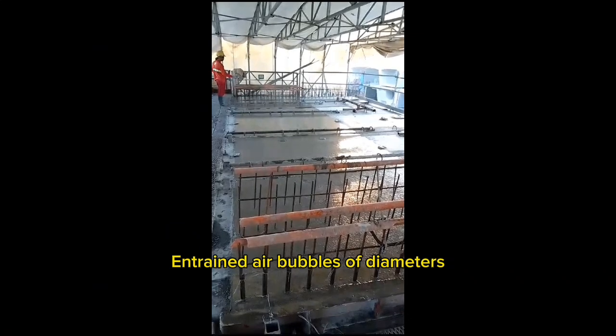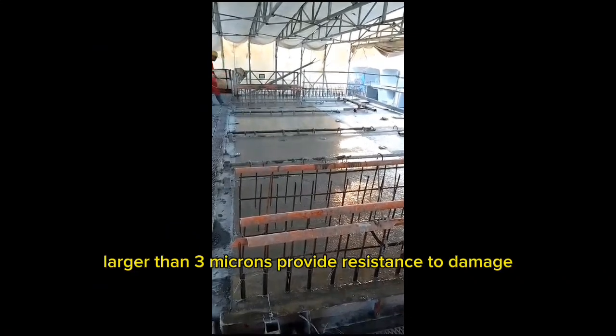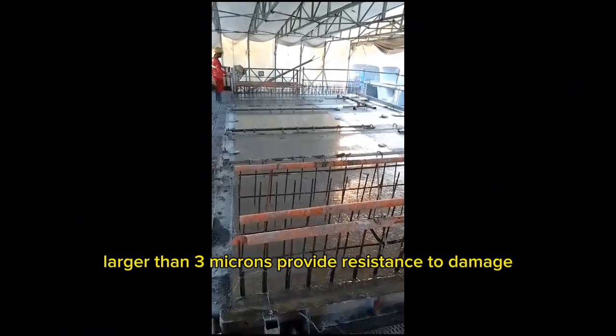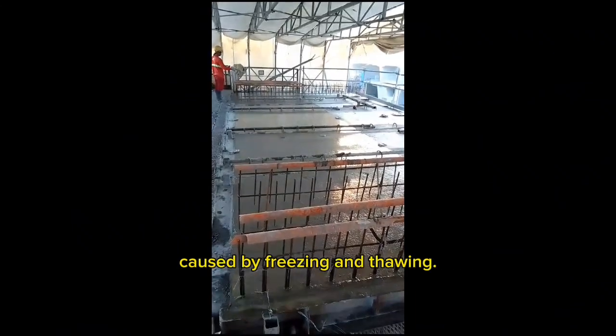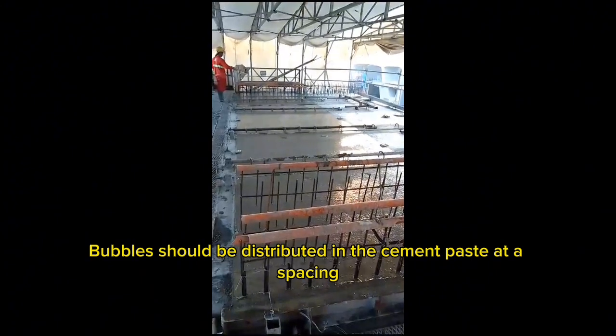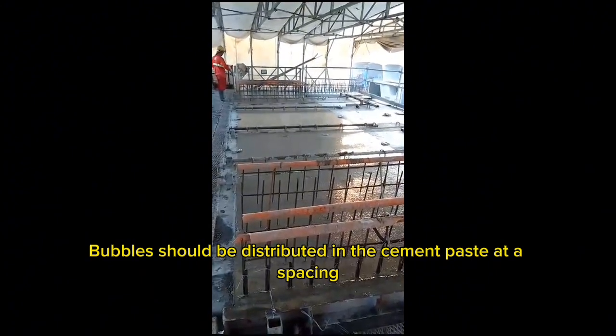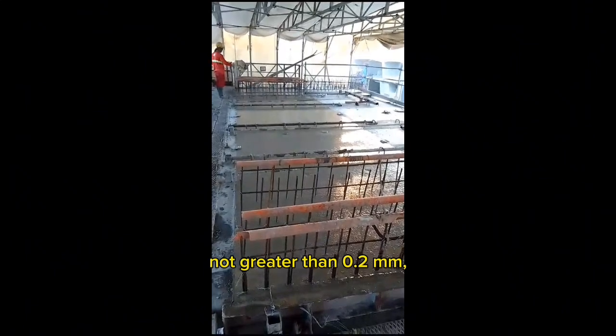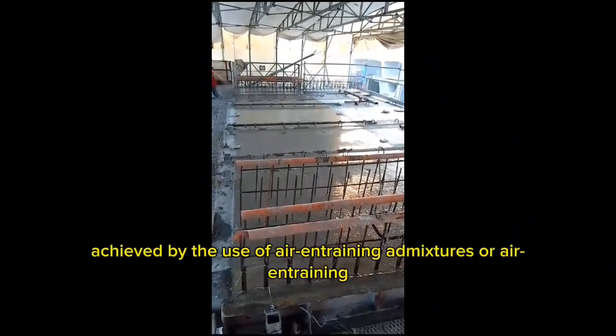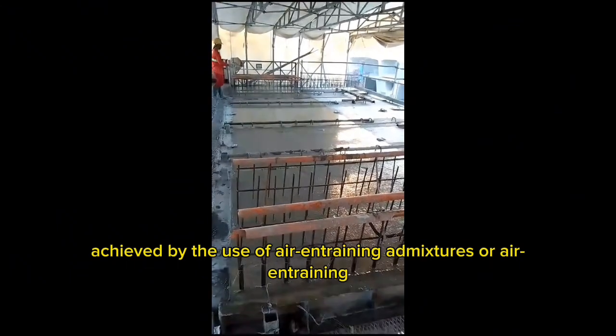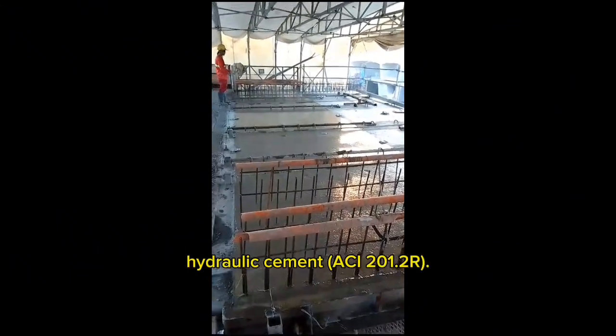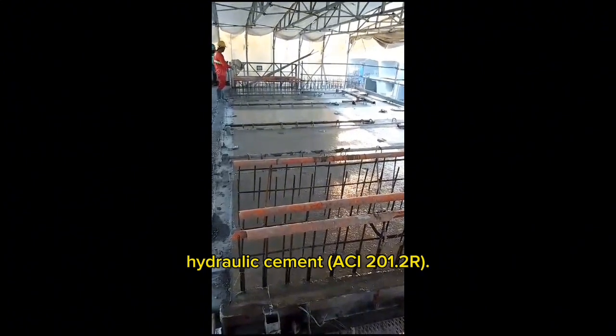Entrained air bubbles of diameters larger than 3 microns provide resistance to damage caused by freezing and thawing. Bubbles should be distributed in the cement paste at a spacing not greater than 0.2 millimeters, achieved by the use of air-entraining admixtures or air-entraining hydraulic cement. ACI 201.2R.